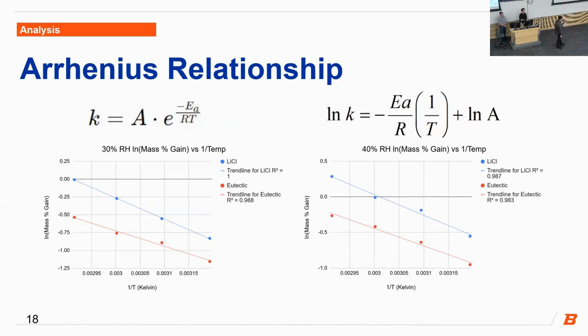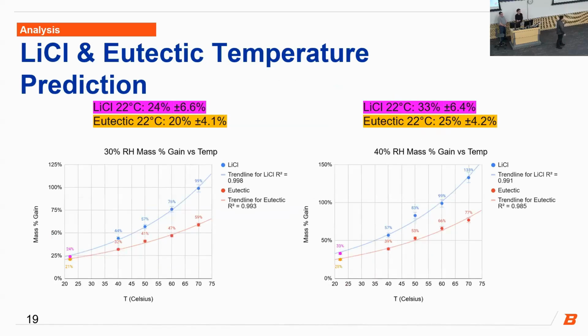So moving forward with lithium chloride and our eutectic, we plotted out the temperature in Celsius versus our weight percent gain. We have the points on each graph for 30% relative humidity on the left and 40% relative humidity on the right. Our points are 40, 50, 60, and 70 degrees Celsius. And then utilizing these points in the graph, we are able to extrapolate what their percent gain is at 22 degrees Celsius for lithium chloride and our eutectic. The pink dots are the lithium chloride and the eutectic is the orange. They're on the left side of each graph.